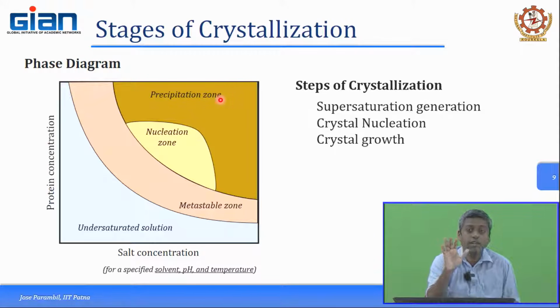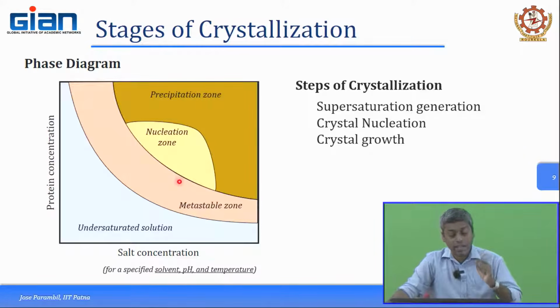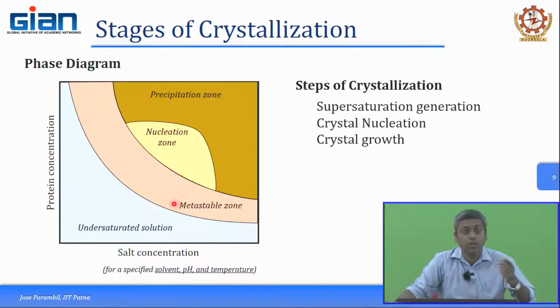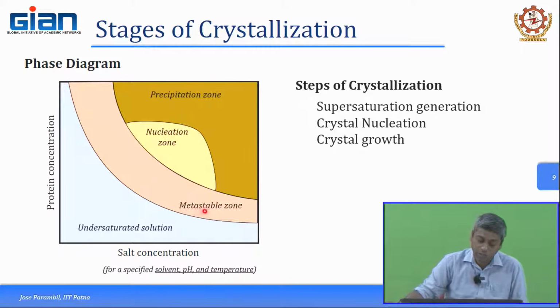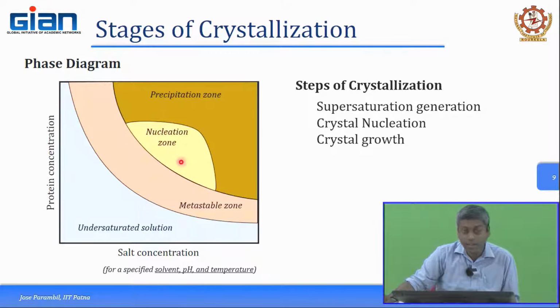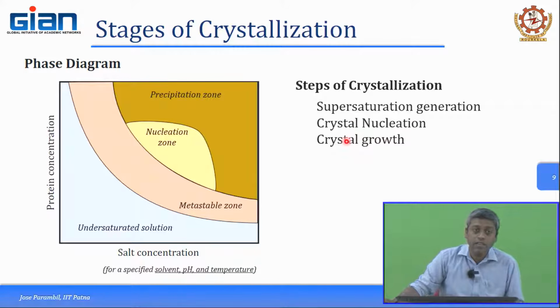In most of the cases, we do not want to go into the precipitation zone. We want to somehow stay within the nucleation zone, nucleate a few crystals and then move into the metastable zone, so that the growth occurs and you get large crystals of your required size. If you are able to regulate this in many ways, then you are practically trying to control the nucleation as well as the growth, then you can get the crystals of the required size, shape, or purity and so on.